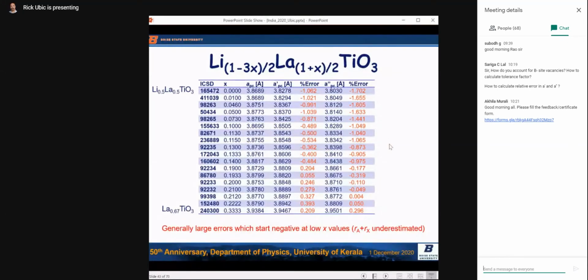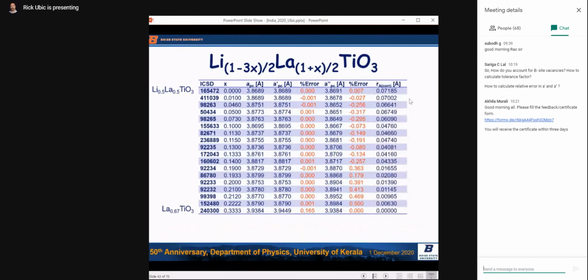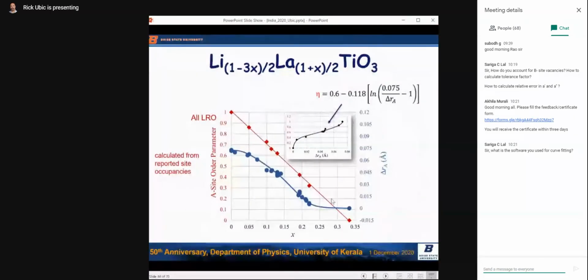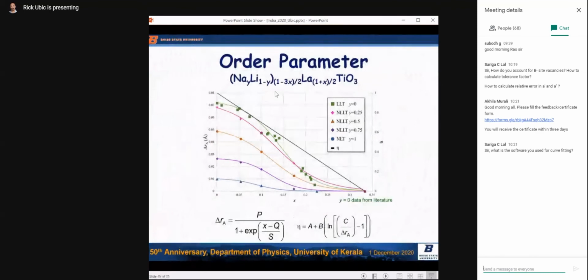So classic, we're underestimating the AX bond length. We correct it with an A correction, and the errors essentially go away, right? And all of these are positive, large to start with, and less as you go up in X. Same sort of thing. There's our ordering parameter. We can stuff in the delta RA that's required, and out pops the ordering parameter. Cool, nifty. All right. So, okay, we made a bunch of intermediate compositions to show that we could do this